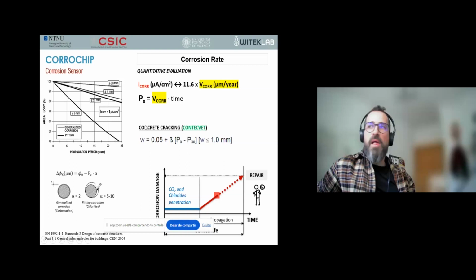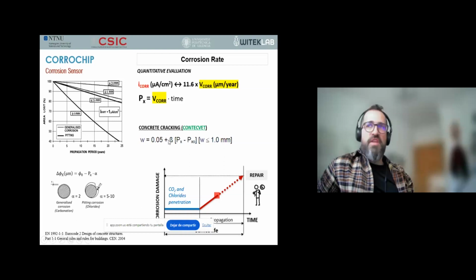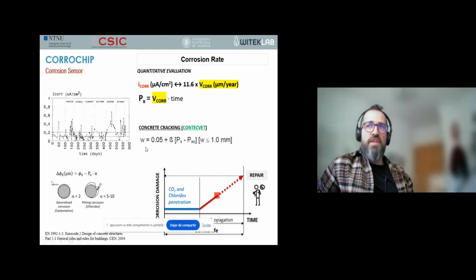In addition, the Contecvet inspection guide proposes a model for estimating the crack width generated by the reinforcement corrosion. So we can predict when some specific crack width will be reached. Okay. So it should be noted also that the corrosion rate fluctuates over time due to variations in temperature and humidity associated with wet-dry cycles. Therefore, it is critical to continuously monitor the corrosion rate in order to make the model estimates as accurate as possible. And that is what we do with Corrochip.